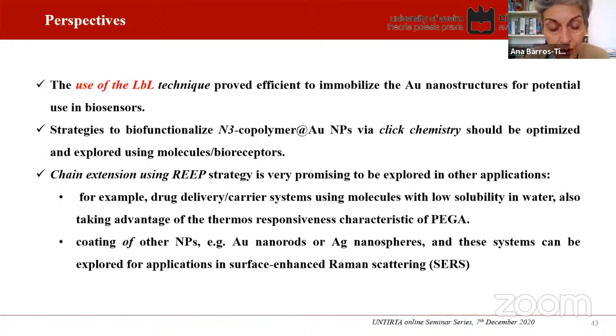So as regards the preparation of more robust structures, specifically the immobilization of these gold nanostructures onto thin films, the use of LBL proved to be rather efficient to achieve that. And strategies to biofunctionalize azide copolymer gold nanoparticles via click chemistry really should be optimized and explored for use with other molecules or bioreceptors. I mean, studies with combinations of antibody and antigen are really a possibility.